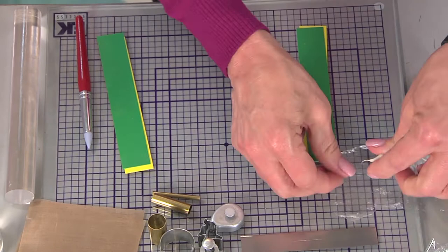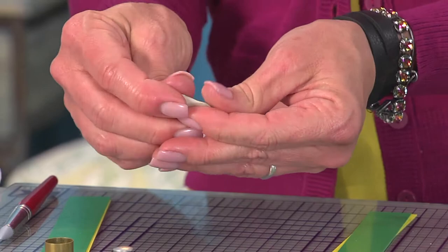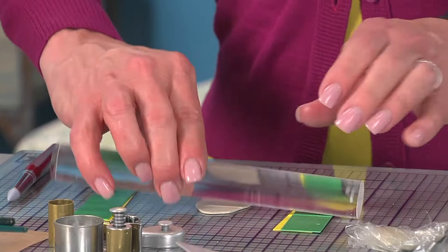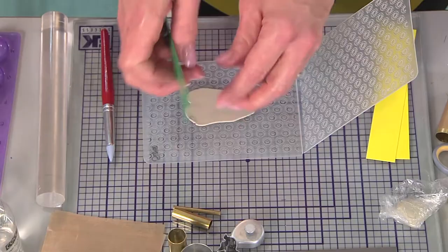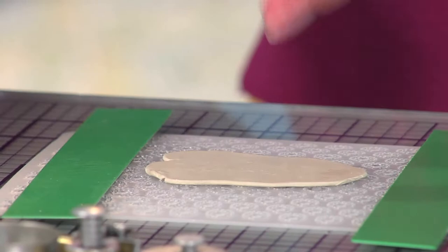I'll wrap the rest back up because it is an air-dry product — you don't want it to dry out ahead of time. I'm just shaping it into a general square or rectangular shape. For viewers who have never seen metal clay before: it's very different from polymer clay. This material is made out of fine particles of fine silver, an organic binder, and water, and it has to be fired at a very high temperature. You need to fire it in a kiln, though there are special kinds you can use with a torch. This particular brand works with both. The clay was rolled out to five cards thick — that's the height of five playing cards — and these measuring sticks are just a more portable, colorful version of that.